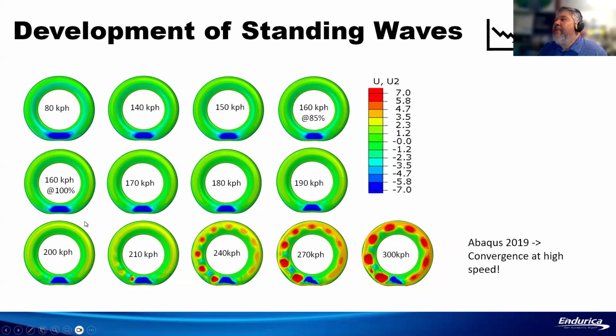And here I'm just showing the out of plane displacement of the tire so that you can see up until about 200 kilometers an hour, the solution is pretty, let's say, tame. If you look in the colors in the sidewall, you can see a little bit, as we increase the speed, you're starting to get a little bit more displacement, right, because of the growth of the tire with the centrifugal force.